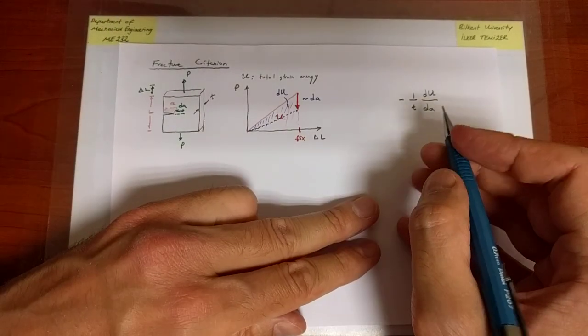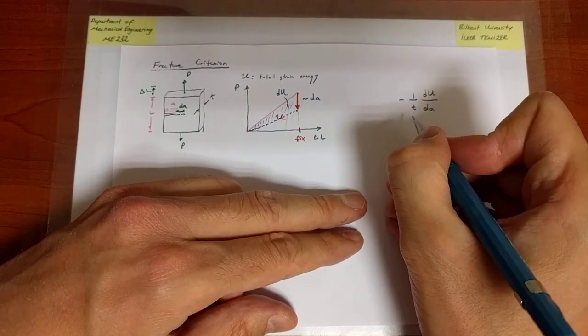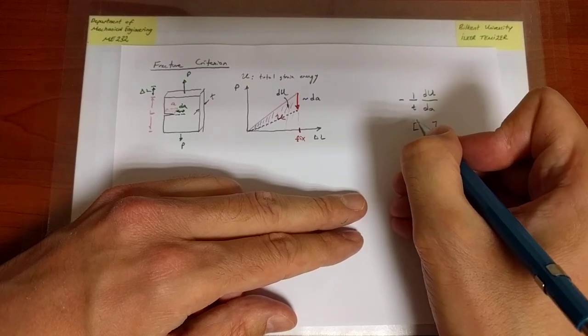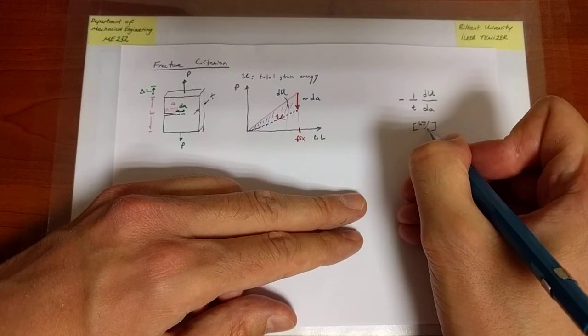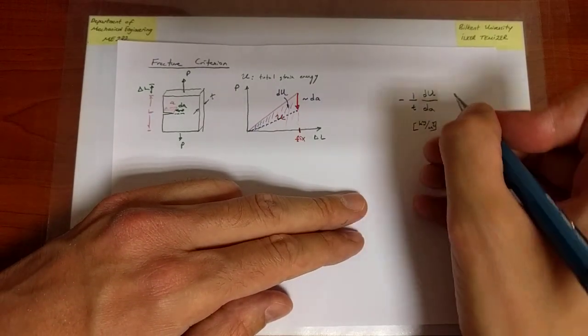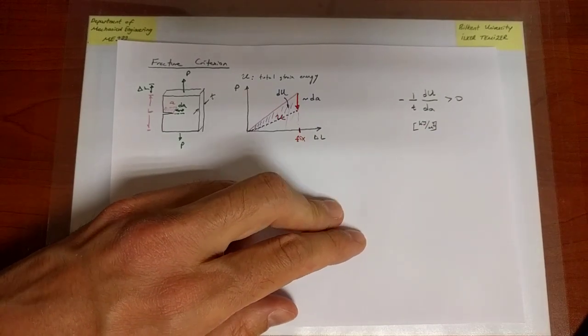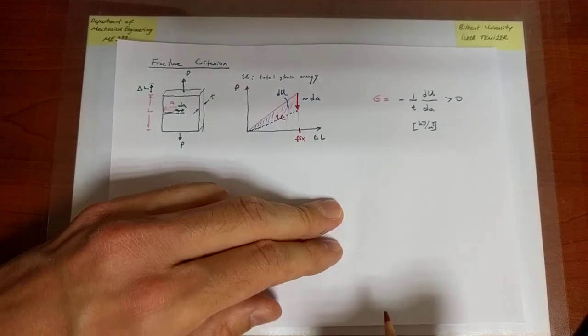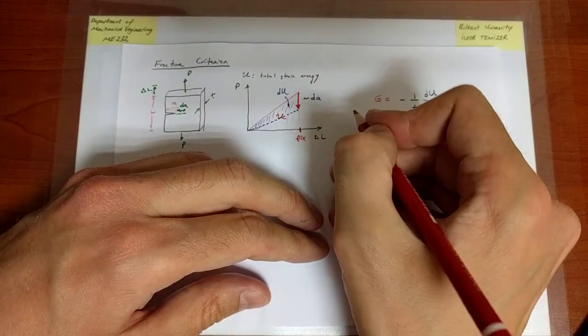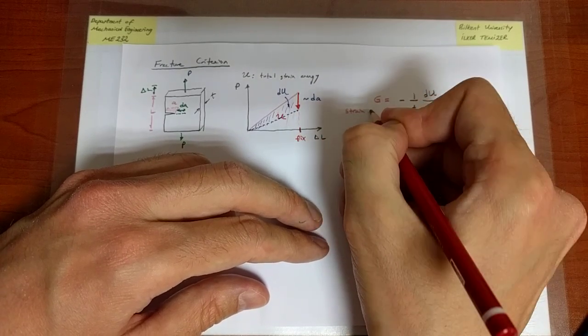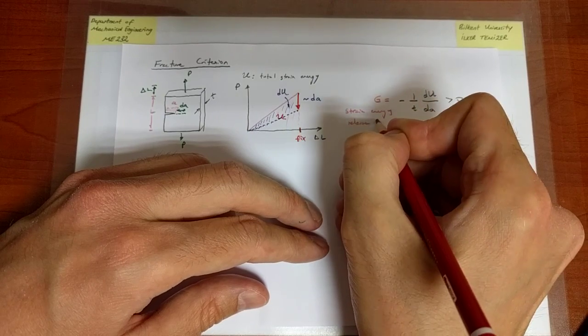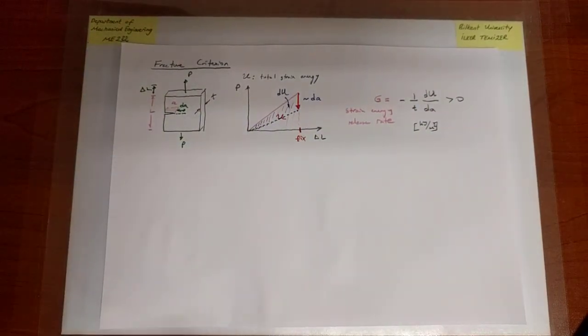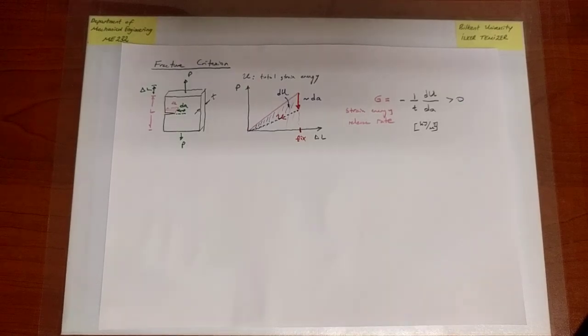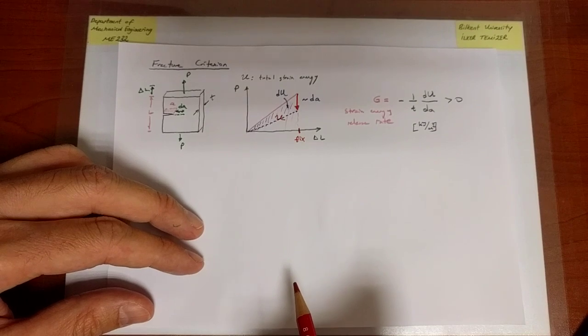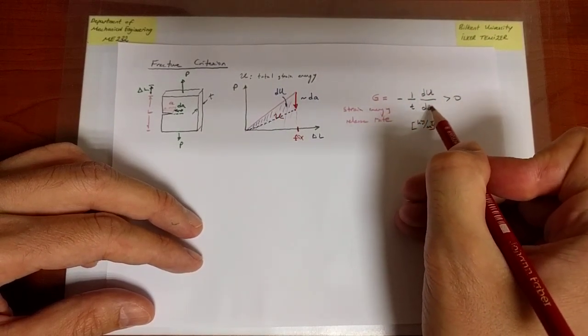So what we have here is a quantity that is certainly in units of energy per meter squared. The typical value to denote that with is kilojoules per meter squared. That's the unit of this quantity. It is greater than 0 and it has a name. It is called G. The symbol is G, the name is strain energy release rate. So here rate refers not to time but rather to the size of crack, how fast the crack increases in size. So that's what the rate is referring to. So derivative with respect to the increase in crack area.